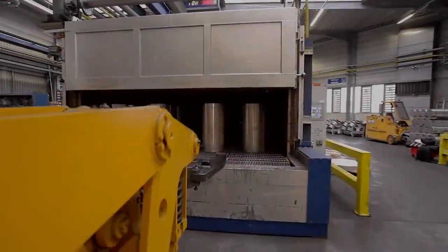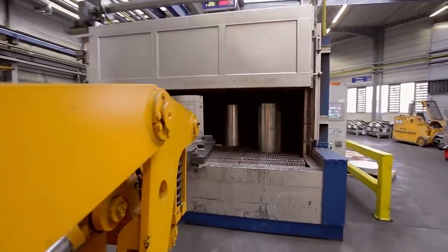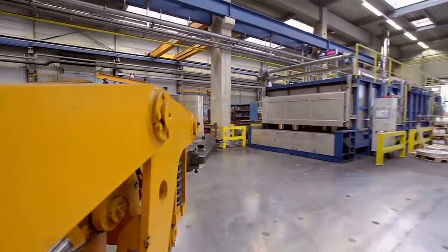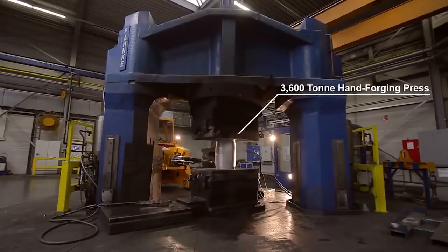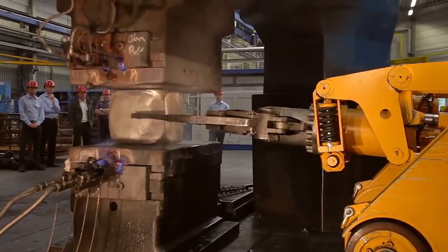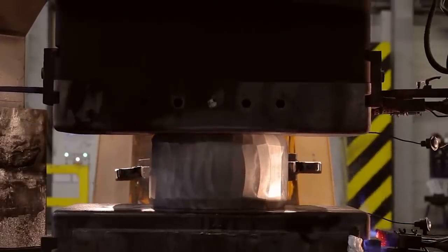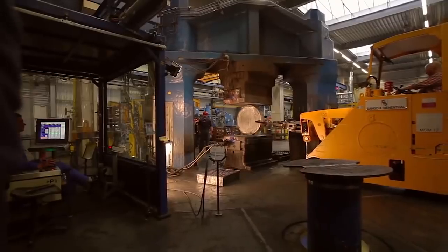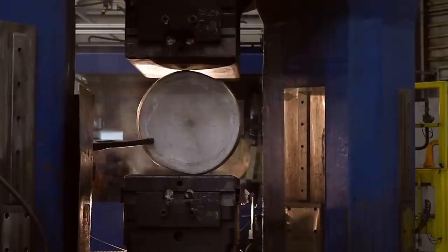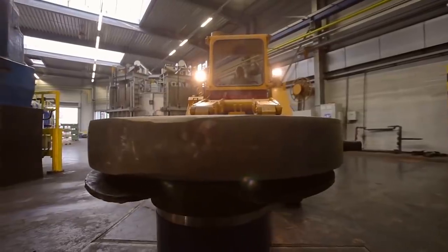These are a very particular set of requirements that forged aerospace grade aluminium fulfils best. To forge these wheels, the team took huge billets of aluminium alloy 7037 and heated them to 390 degrees and compressed them with a 3,600 tonne forging press. The forging clamp operator here deserves credit for the insane precision, taking this cylindrical billet and forming it into a compressed disc. This is the blank, which will be passed to a milling machine to mill the wheel into its final shape. Transforming the cast material into this forged material makes the material vastly stronger.